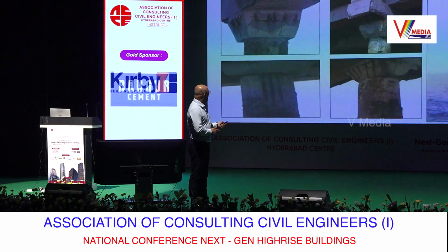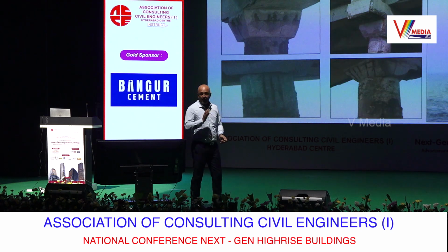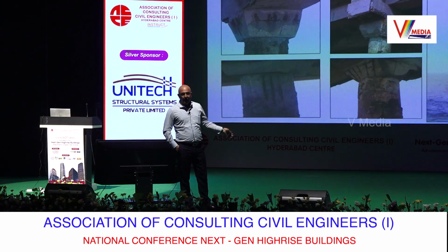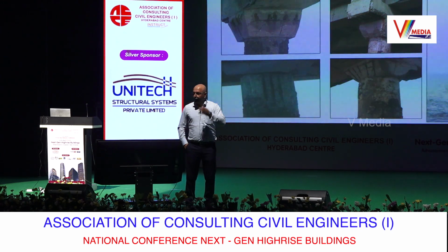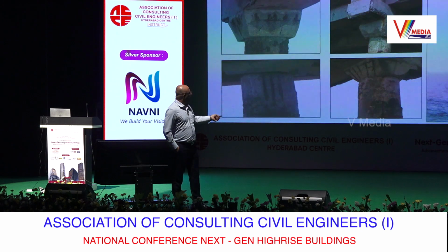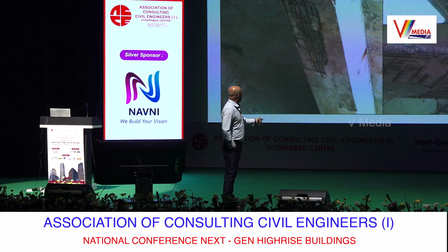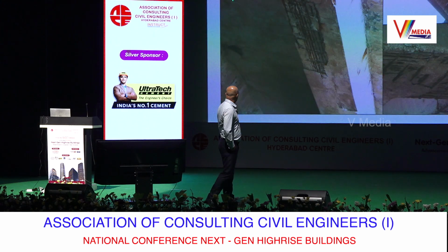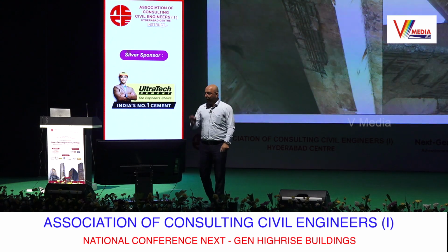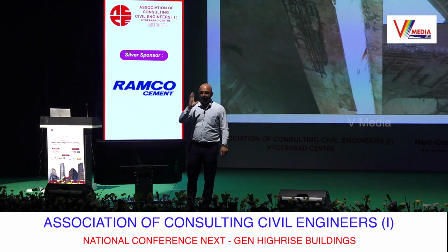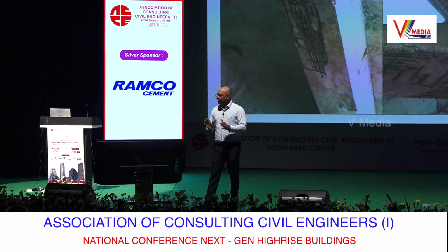I'll show you the technique. This was the condition of the repaired members. So this jetty was regularly repaired. Every 2-3 years they used to repair, and the damages used to come again. You can see the condition of the repair here. These are all repaired portions. The problem was, they were not treating corrosion properly. They were only layering it with high strength microconcrete and high strength mortars, and corrosion was not treated properly.